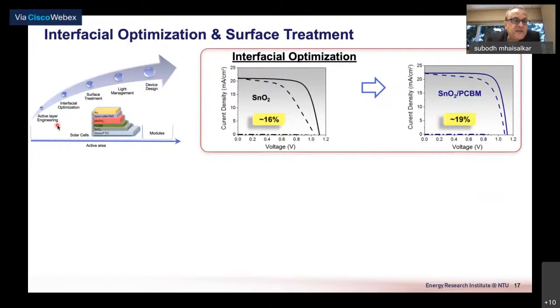So the first step in this is really active layer engineering, where you choose the deposition of the materials. In our case, we essentially fix the deposition of lead iodide and change the temperature for the deposition of methyl ammonium iodide, and we found out that the optimal is in the range of about 100 degrees.